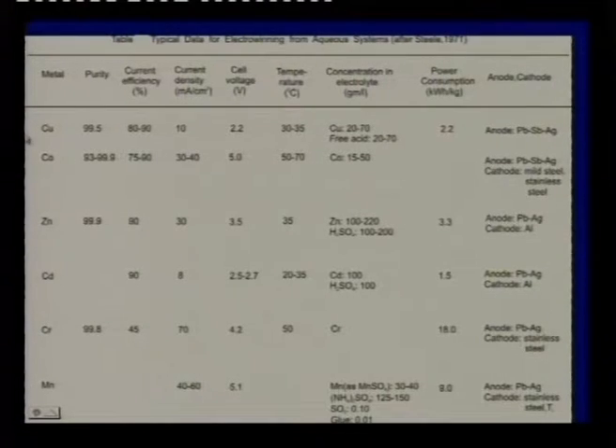I have given you some data to show what kind of purities are obtained. You see, during electrowinning from aqueous solutions, we get purities of 99, 99.9, 99.8 percent. Very often we have to have such purities, because unless the solution is pure, you cannot do zinc electrolysis, because zinc is normally above hydrogen. It is only in a pure solution that you can have activation overpotential, where the hydrogen potential exceeds that of zinc in the EMF series. So, we need extreme purification of the zinc leach liquor.